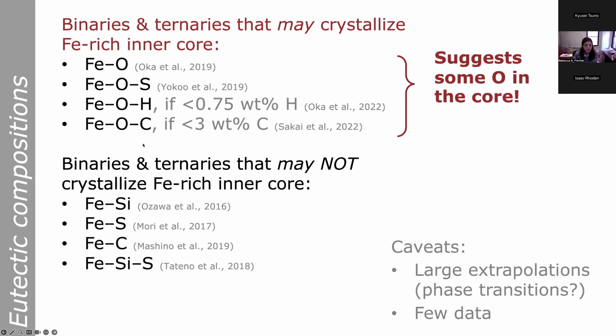And what you will notice is that all of the ones that seem like they could work have oxygen in them. So that suggests that there should be some non-trivial amount of oxygen in the Earth's core in order to be on the right side of the eutectic to be crystallizing an iron-rich inner core. Again, this requires significant extrapolations in most cases. There's also not a ton of data on many of these systems because these experiments are so difficult and labor intensive.